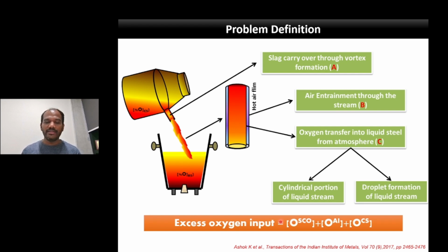Okay, we have extensively studied and modeled this excess oxygen input through a thermodynamic model and mathematical model. That is a separate paper. One can refer to that to know how the excess oxygen input can be calculated. However, the present work, what I'm presenting here, is the quantification of the slag carryover. Not only the excess oxygen, as a whole the slag carryover, we are quantifying through FactSage simulations.